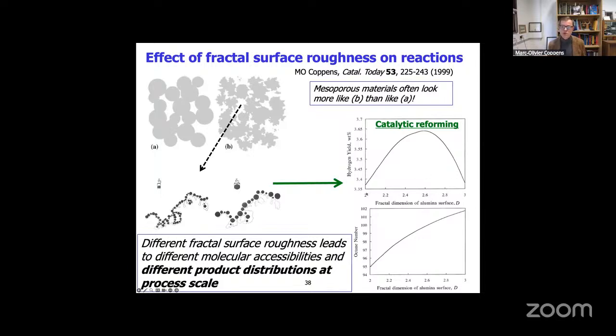If the surface is very smooth, you have a low yield. If it becomes rougher, you have more access to the surface, but the diffusivity becomes lower and lower. The Knudsen diffusivity, at least. Hydrogen can get trapped also, and this can lead to selectivity issues, where it can overcrack desired molecules in the catalytic reforming. And that is why for too rough a surface, the yield of hydrogen goes down. Okay, so this is just an example of why this matters.